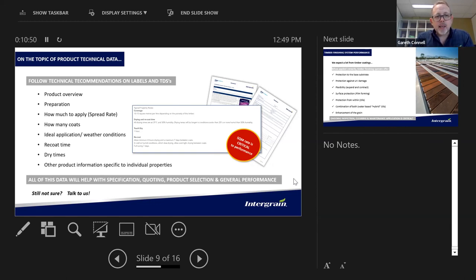The ideal application conditions and weather conditions, usually we say somewhere around 25 degrees Celsius at around 50% relative humidity are the ideal conditions. Will give you a dry time of XYZ. If it's going to be cooler, if it's going to be hotter, that will affect your dry times and also your spread rates, so something to be mindful of and underscores how important it is to read this technical information as well, particularly when you're talking to your contractors when they're applying these materials.